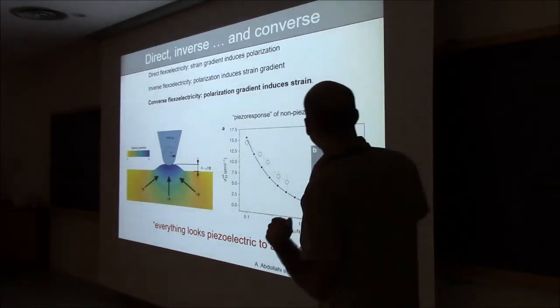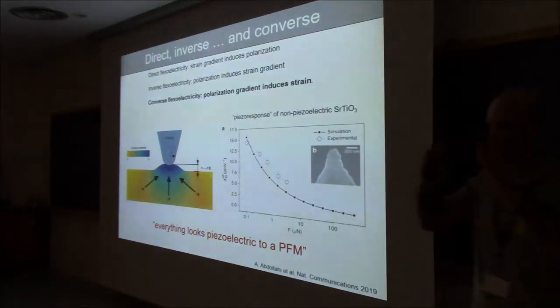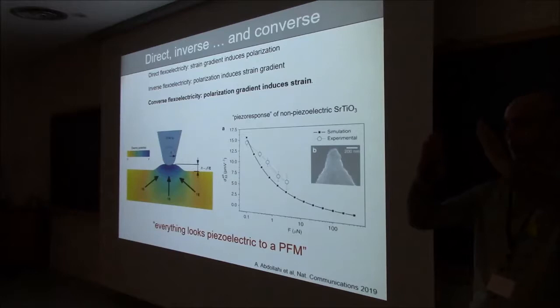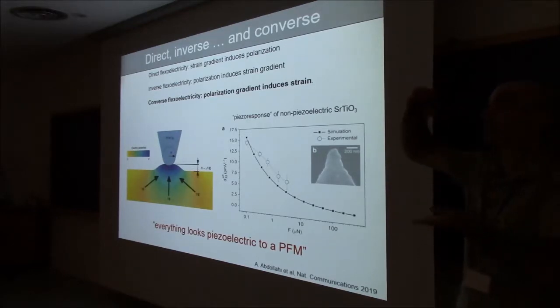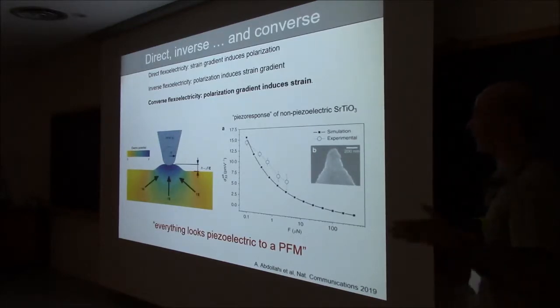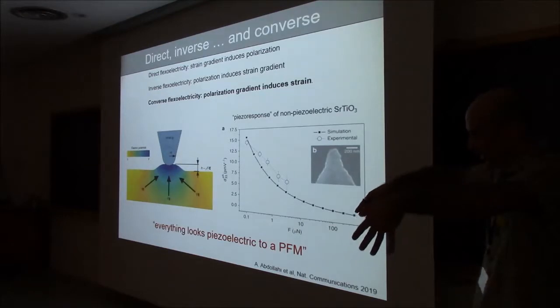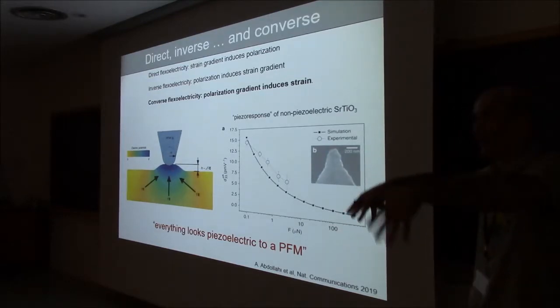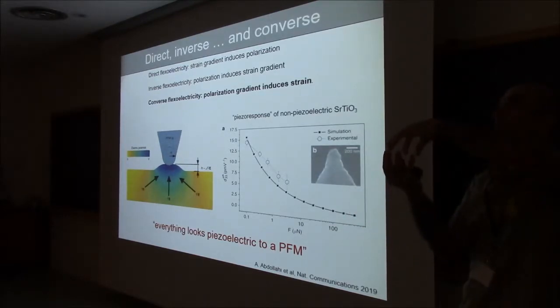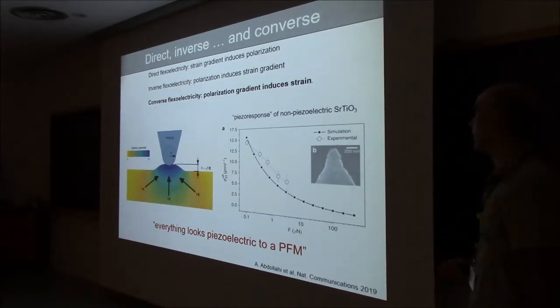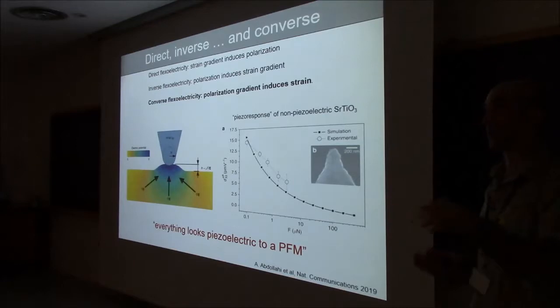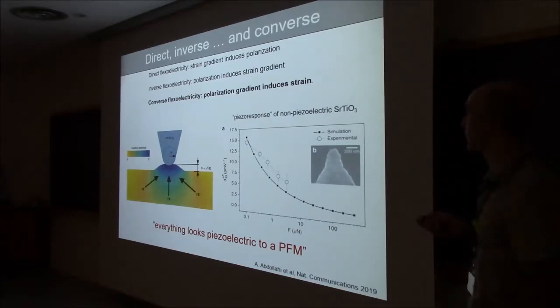Yeah? In fact, the first time that this was measured was by making truncated pyramids that had more or less a linear shape. They applied the voltage between the two things, and the electric field was distributed linearly on the pyramid, and that would make the whole pyramid stretch or compress. You will see that that's also the way in which normal flexoelectricity can be used.